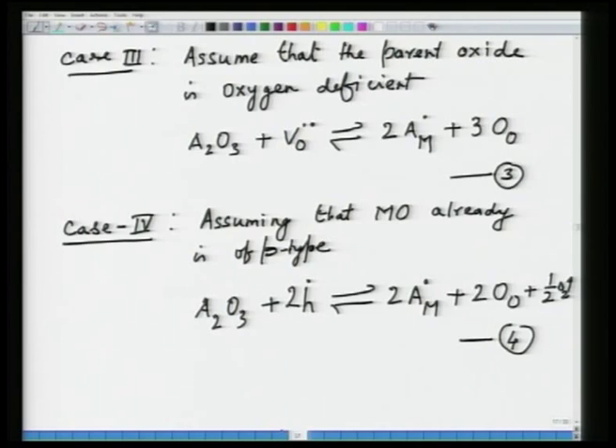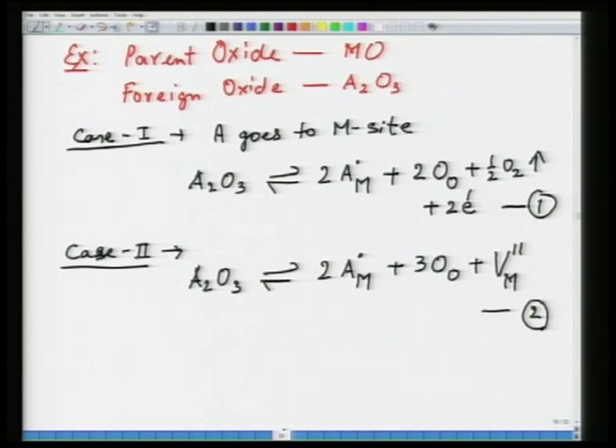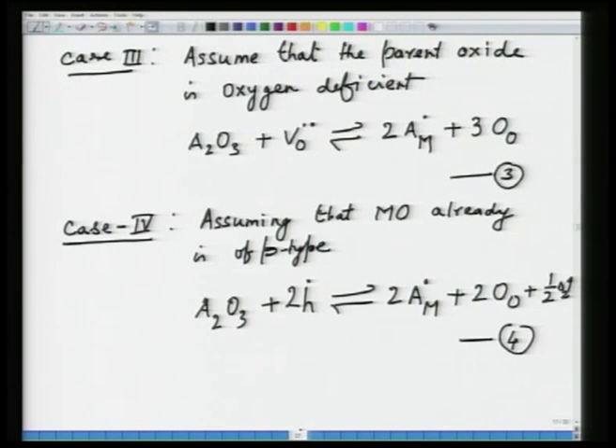In the previous slide we looked at when the material was stoichiometric, it did not have any defect to begin with. Then what is the scenario? You can have creation of a metal vacancy or creation of 2 extra electrons, or alternatively if the metal oxide was already oxygen deficient or contained holes to begin with, then these holes or oxygen vacancies could be compensated by presence of these impurities. So, as a homework you can do, for example, as an exercise